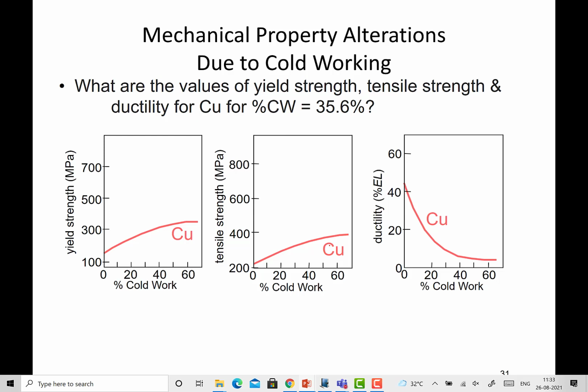Just for an example, if you see when the copper is taken, the way by which the properties will change for copper with the increasing percentage of the cold working. Okay, so let's say the copper, when it is worked, yield strength increases from around 150 value to around 350 value with the change of the percentage of the cold working for the copper. Likewise, there is a change in the tensile strength and reduction in the percentage elongation. So this change is related with their ability to work harden.